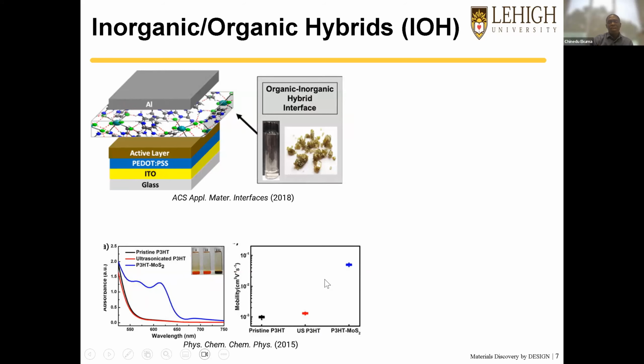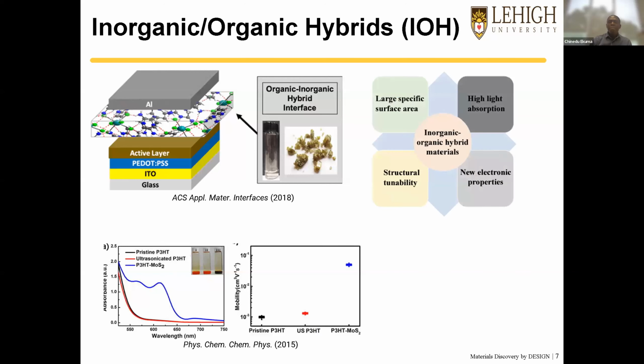where photoactivity could be generally enhanced. Also, as you can see, when we have this hybrid system, we generally can drive the mobility to orders of magnitude larger than either of them staying apart. So generally, when we have these interfaces, we do have materials with enhanced and improved properties that we can easily tune. Because of their nature, they have these large area surfaces, which could be optimized for photocatalysis and solar cell absorption. There is tons of structural tunability that we can engineer, and new properties generally emerge.